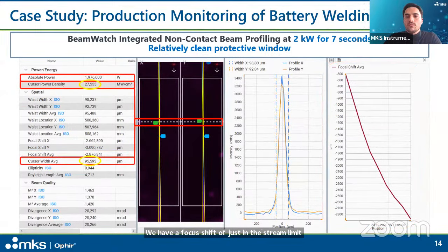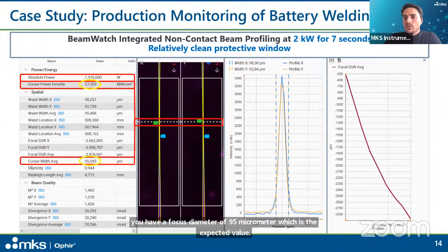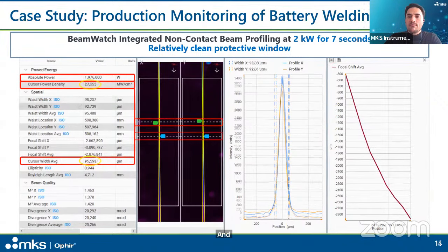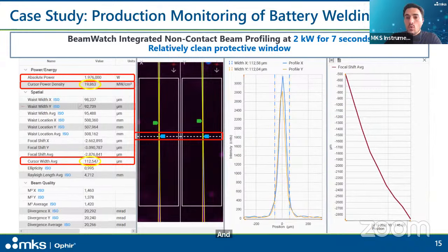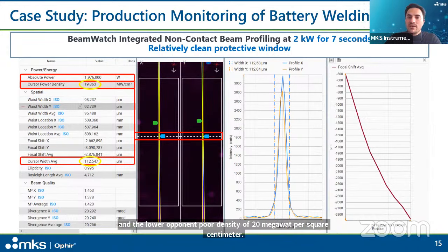At the focus, where the cursor is, that is the dashed line, you have a focus diameter of 95 micrometers, which is the expected value, and a power density of 27 megawatts per square centimeter. But at the workpiece, 3 millimeters deeper, we are out of focus. In this case, we have a bigger beam diameter of 112 micrometers and a lower power density of 20 megawatts per square centimeter. So in this specific case, the effect still had an acceptable impact on the quality.